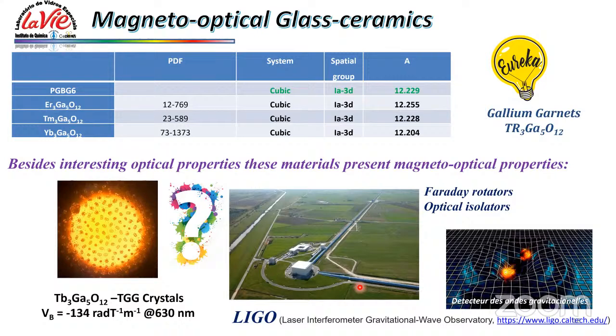So we changed the composition of our glass. We put some terbium there, and what you see here is the amount of crystals increasing. As a matter of fact, we gave more time to cool the glass. So these crystals are formed during the cooling of the glass. If you control the quenching rate, we increase the amount of crystals inside the glass. And when we characterized this, we got the TGG crystals.